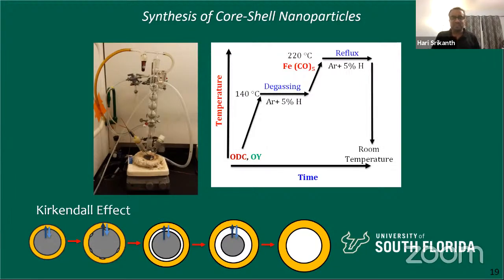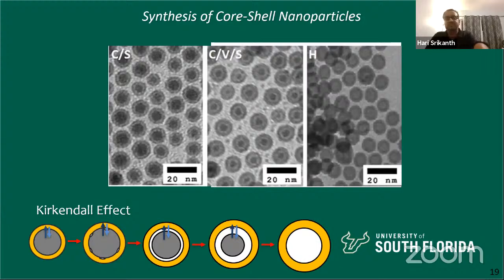But unfortunately, it's not good for us because as a function of time, the material itself is converting from core shell to hollow. Which means the magnetization is continuously changing, and it's not a good, reliable system for SAR. We did a lot of studies. This beautiful set of TEM images my student took to look at the progression of going from core shell, where the core is now becoming smaller and eventually hollow.